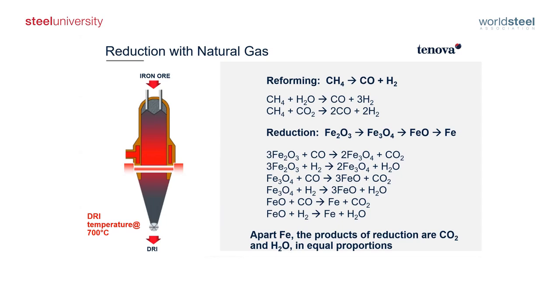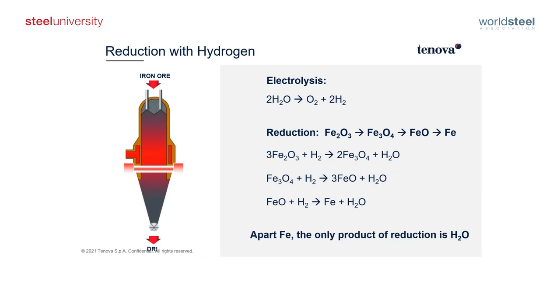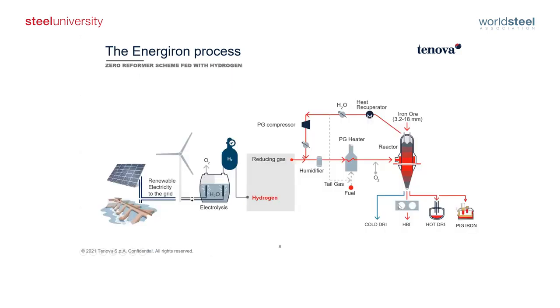If one operates the module by green hydrogen only, it doesn't change much, except there is no longer carbon monoxide in the reduction gas mix, you just have hydrogen. In such case, by having only the hydrogen operating the reaction of reducing the iron oxide into metallic iron, the only byproduct is steam. So the scheme of the HYL Energiron modules is natively able to operate with 100% hydrogen,